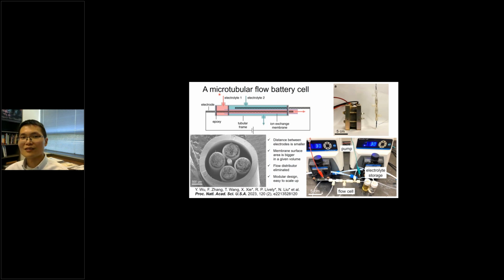What we invented is a microtubular flow cell for flow batteries. This is what a typical flow cell looks like. They adopt a planar configuration, with a membrane in the middle as a two-dimensional membrane. And our device is a tubular structure, and the membrane is actually a tube. They look like this. These are 4 Nafion membranes, and inside you have 1 electrode, and outside the membrane you have another electrode. The reaction happens on the 2 electrodes, and the ions pass through the membrane. This entire thing is less than a millimeter, about half a millimeter. So it's a very, very skinny tube, and you can bundle them together to form a bigger module.